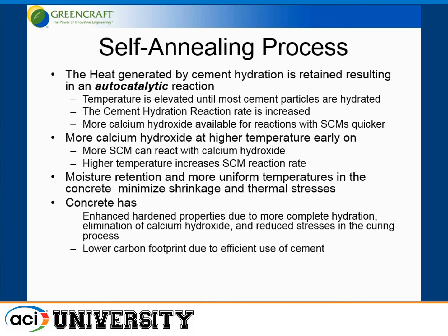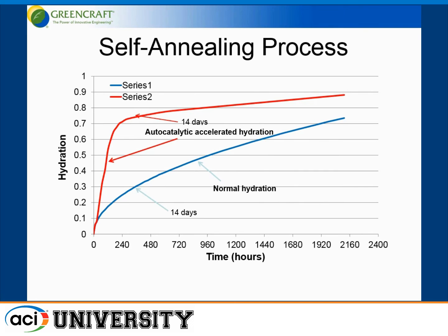So now we get a concrete that has enhanced properties due to a more complete hydration, elimination of calcium hydroxide, and reduced stress in the curing process, and all while we're reducing the carbon footprint through more efficient use of the cement, and primarily the energy that's embedded in the cement. This is an illustration of what the self-annealing process accelerated hydration looks like versus a normal hydration would look like.